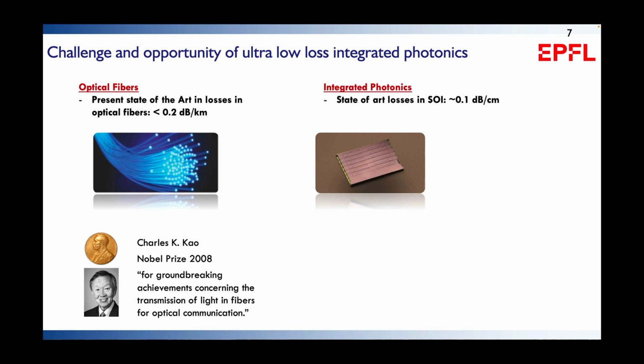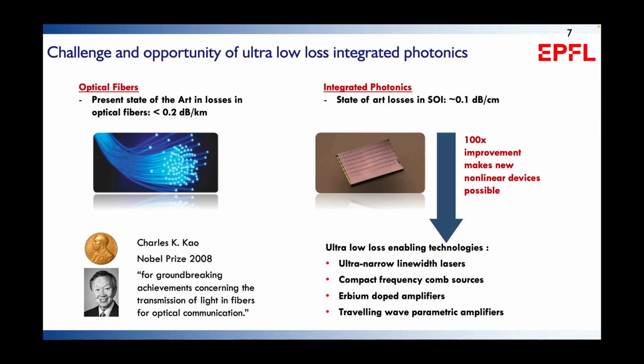What I'd like to tell you about in this presentation is mostly two classes of materials. The first is a very well-known semiconductor material but new to optics, and that's silicon nitride. I'd like to show you that this allows circuits that don't close the gap to optical fibers. In fact, we still have 2 or 3 orders of magnitude to go, but we can now make circuits with a factor of 100 lower loss than state-of-the-art silicon photonics. So we now have losses that are not dB per centimeter, but really dB per meter.